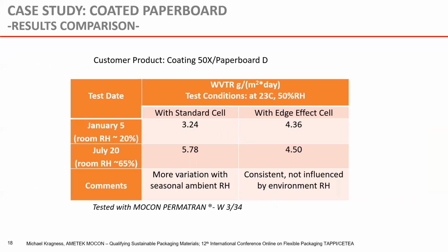So just to discuss a little bit about a case study that we did with this edge effect cartridge, we ran a water vapor test at 23°C and 50% relative humidity. We ran the same test at 2 different times of the year. We ran it with our standard cell that would have the edges left open to the atmosphere, and we ran it with our edge effect cell that's actually covering the edges.